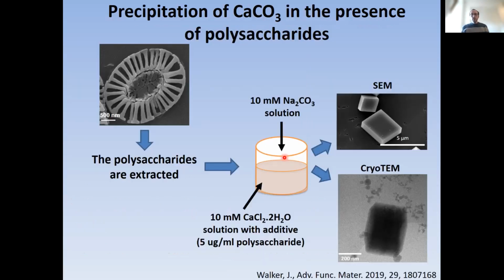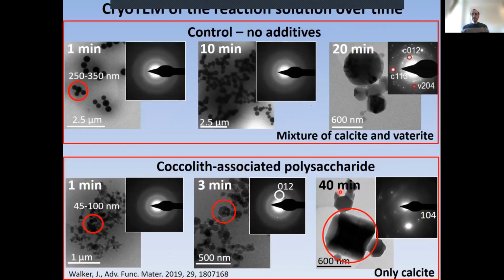So what Jessica did was relatively simple. We got polysaccharides extracted from the coccoliths. We put them in a supersaturated calcium carbonate solution under conditions that would favor the formation of vaterite, and then collected samples over time and froze them and imaged using cryo-TEM. And these are the images we got. So this was done on Gephyrocapsa oceanica, so it's a different species. And this is the control without any additives.